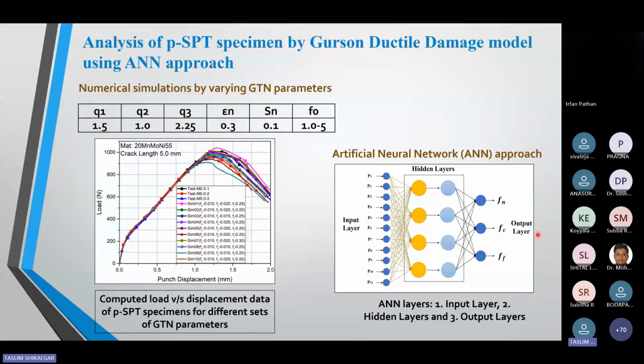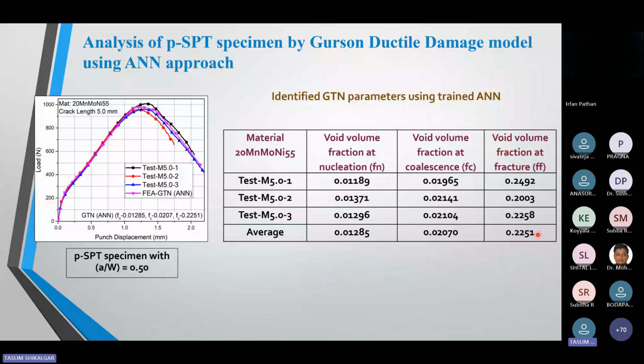And I have obtained them here. You can see I obtained 3 different values for 3 specimens. With the help of these values, I took the average. This is my average value. These are the nucleation, coalescence, and failure parameters, and I used these 3 damage parameters to perform the numerical simulations of the 5 mm crack length specimens.